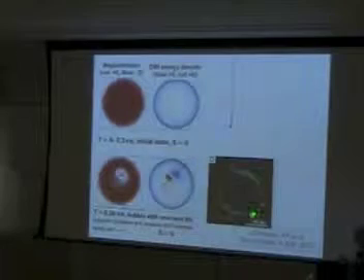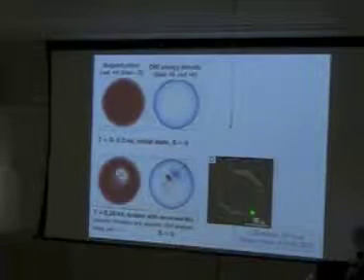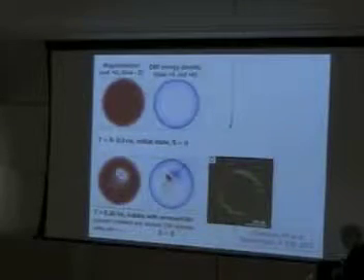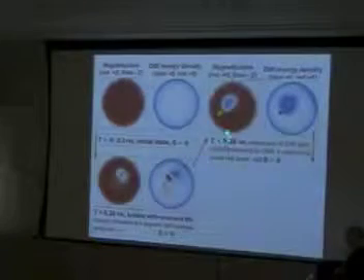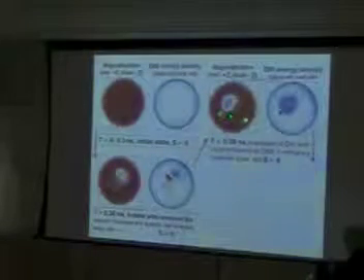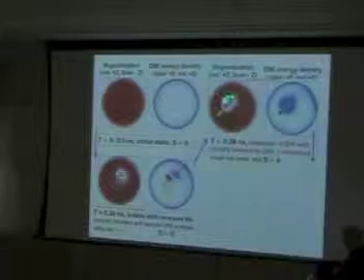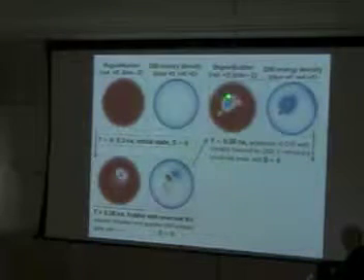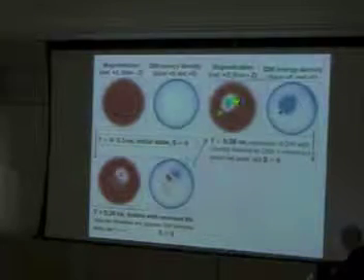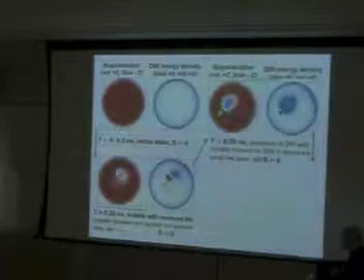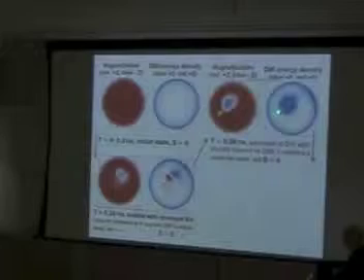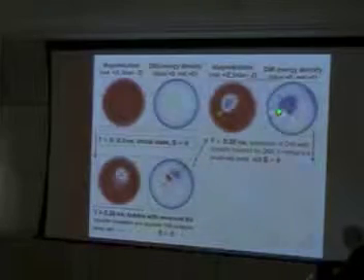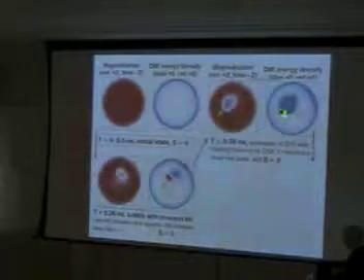Bloch line, because with the bubble the thickness was not so small. And the next step is that progressively, with the Dzyaloshinskii-Moriya interaction, the part of the pseudo-domain wall in agreement with the interaction progressively compresses the other part into this small defect of very large exchange and DMI energy.